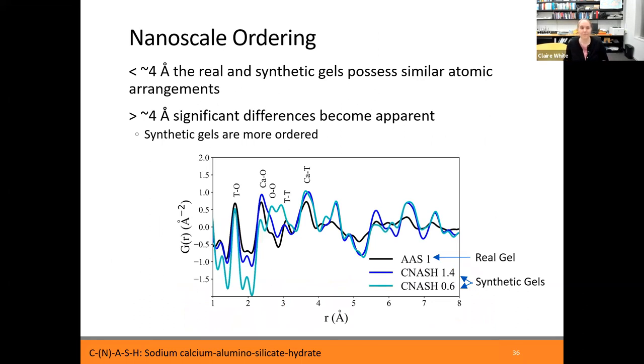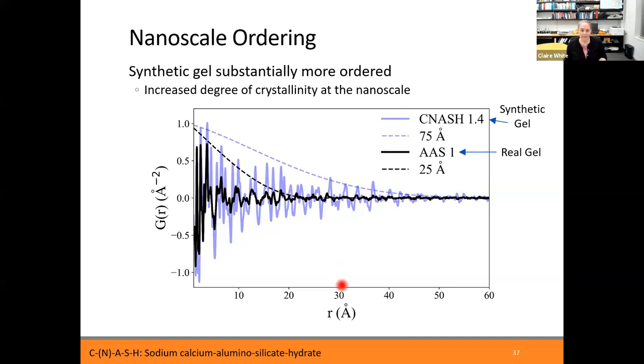Very much lastly, we're going to look at nanoscale ordering of these gels. So I've plotted out to a lot further in R space, in real space, for the paired distribution function. And you can see how the correlations, these atom-atom distances, die off a lot more quickly for this dark sample that's denoted here as AAS compared to the purple sample. There's a difference between these two. One is the gel that's in alkali activated slag. So it was in a cement sample and we were able to subtract out other contributions from other phases and look at the contributions just from the gel. And then the purple is just a synthetic gel. There's clear differences in the nanoscale ordering, how ordered the gel is, which can have implications for how people currently use these synthetic gels to understand the Portland cement system.